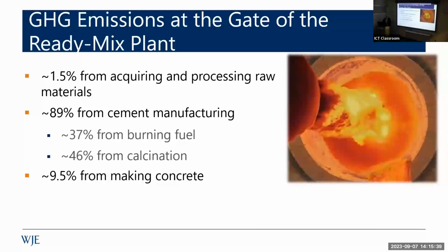Calcium CO3. We're driving off CO2 to get calcium oxide. Calcium oxide reacts with silica and alumina to give us Portland cement. So 46% of all of the CO2 associated with manufacturing concrete, this is concrete, not just cement, is from calcining limestone. So no matter what we did on energy efficiency, in grinding efficiency, and in concrete production, and everything else, we still got basically this big thing right here from burning the limestone, driving off the CO2.